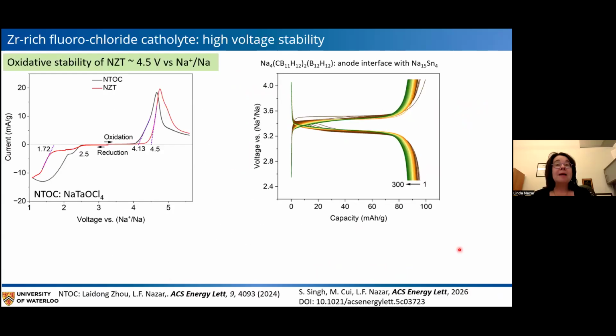So this fluorination increases the oxidation stability up to 4.5 volts versus Na plus sodium. And here we just compare a CV with our previously reported sodium tantalum oxychloride, and I'll be talking about oxychlorides later. But suffice it to say at this point that we have a distinct increase in that oxidation potential, which is beneficial for high voltage cathodes.